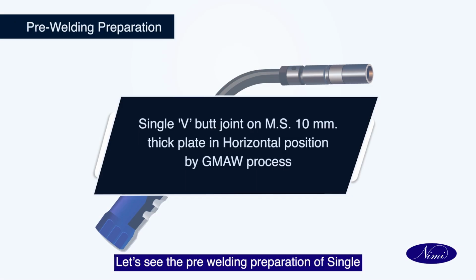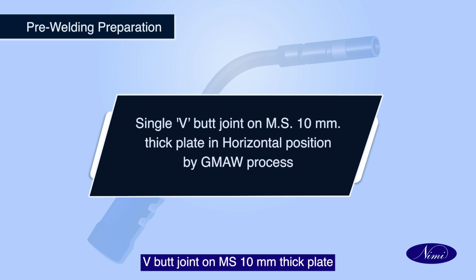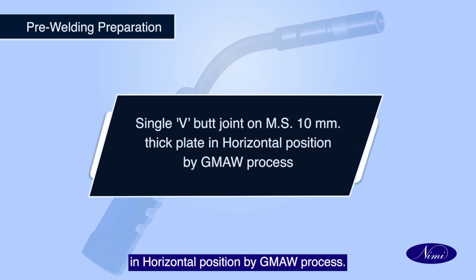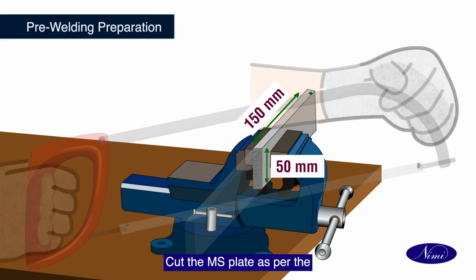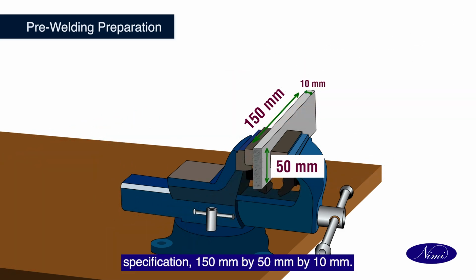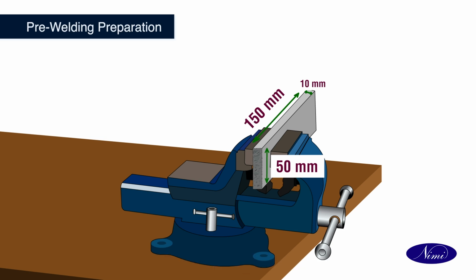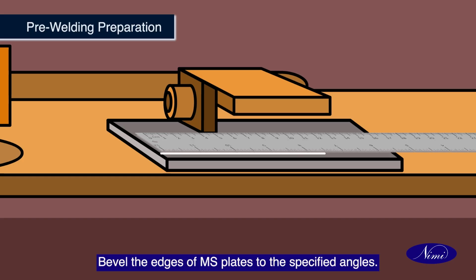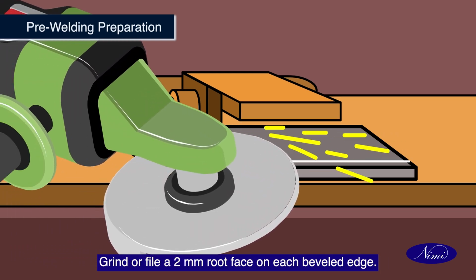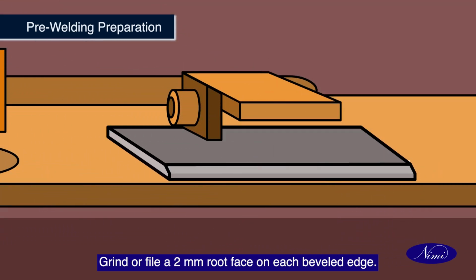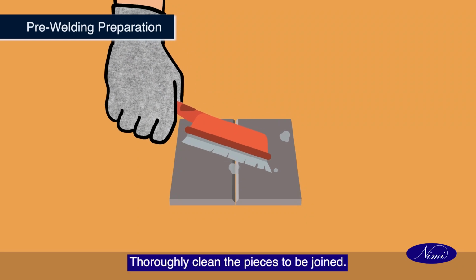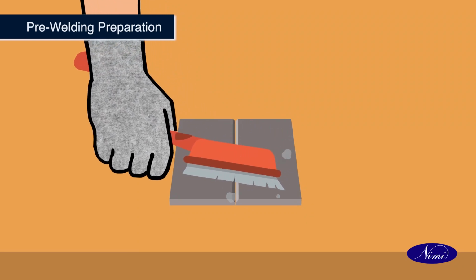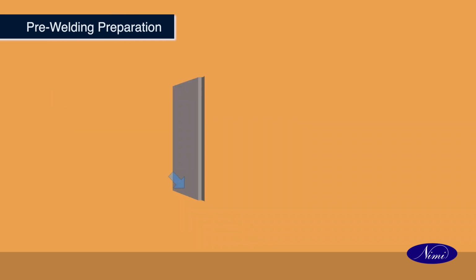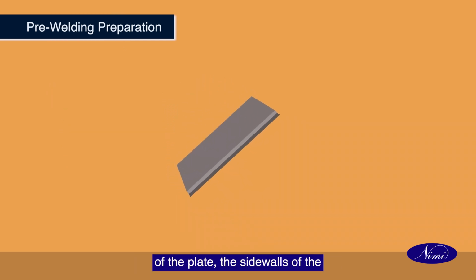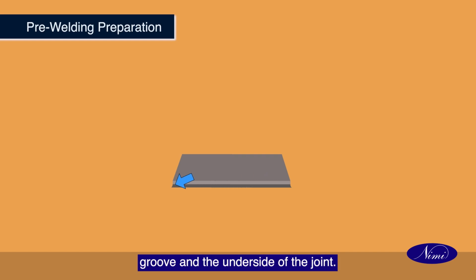Let's see the pre-welding preparation of single V-butt joint on MS 10 mm thick plate in horizontal position by GMAW process. Cut the MS plate as per the specification, 150 mm by 50 mm by 10 mm. Bevel the edges of MS plates to the specified angles. Grind or file a 2 mm root face on each beveled edge. Thoroughly clean the pieces to be joined. Pay particular attention to the top side of the plate, the side walls of the groove, and the underside of the joint.